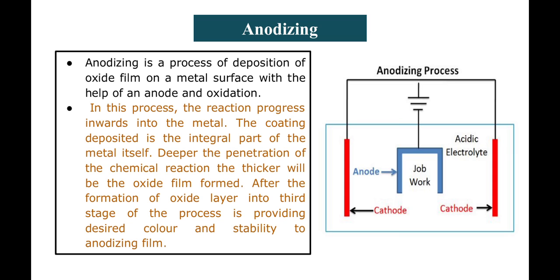The color of the deposited layer depends upon the selection of the acid as the electrolyte. Sulfuric acid provides a thin transparent film over the metal surface, and the anodized metal exhibits its own natural color after the process. Chromic acid can also be used as an electrolyte to deposit an oxide layer, and it provides a milky white color to the surface, which can also be changed to gray depending upon the variation of the bath temperature. Copper and its alloys are not anodized by this bath.